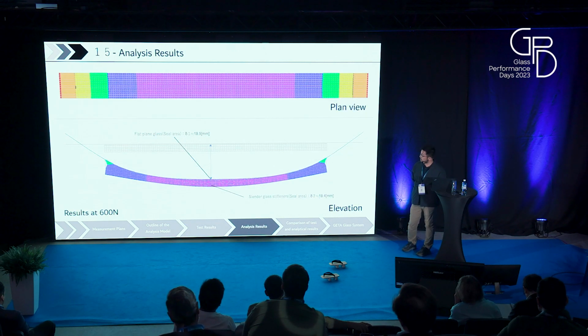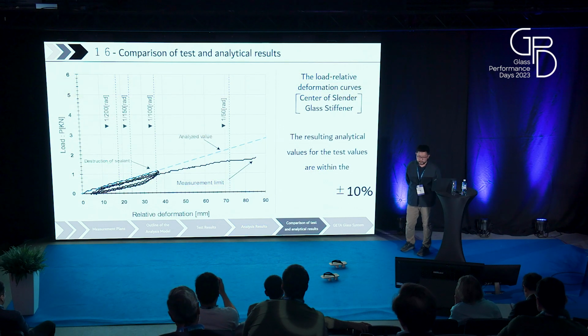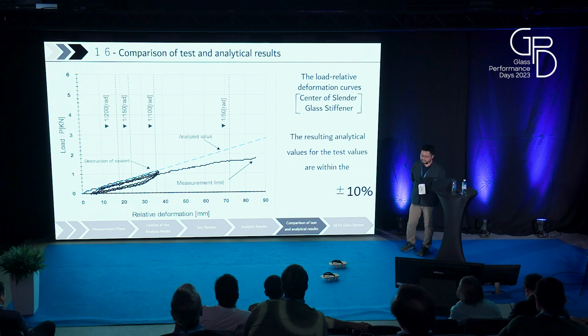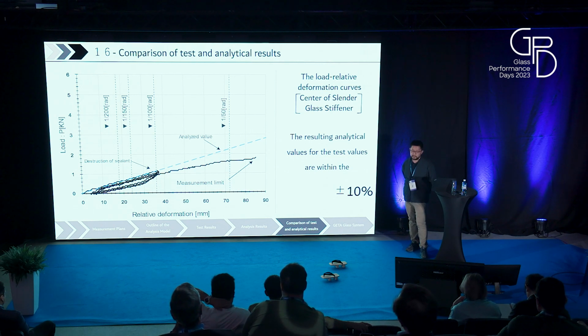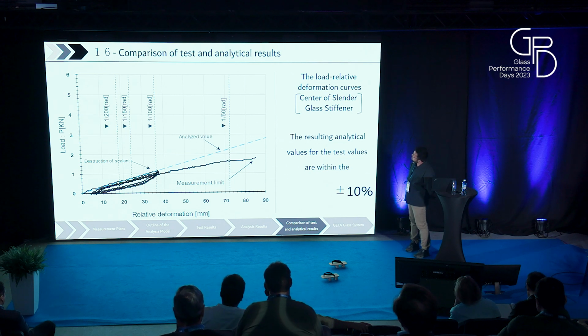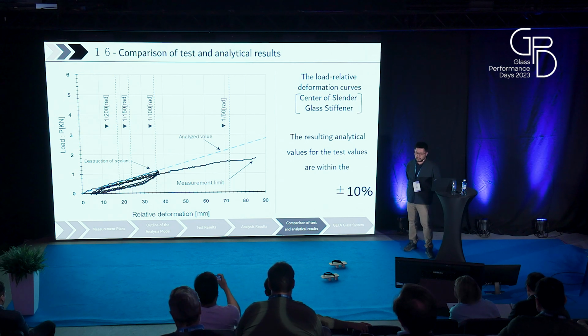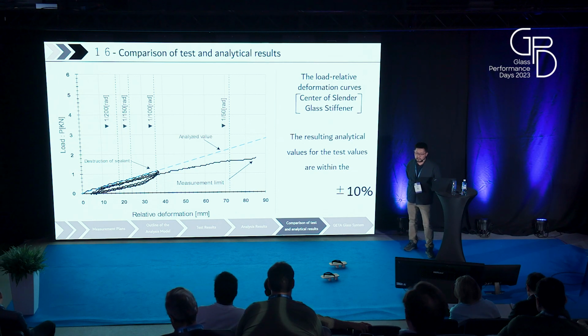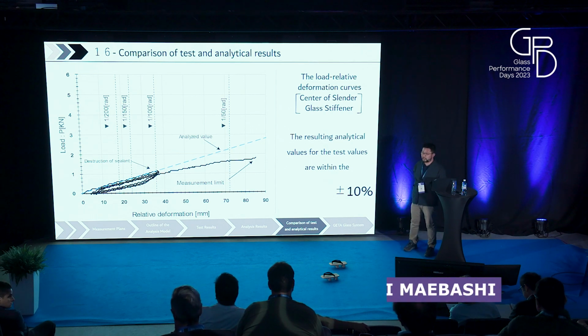And this is the analysis result. Also, we have compared the analytical values and test values obtained from the bending load experiments, and here are the analysis results. As a result, we could confirm that the difference between the test specimens with flat glass at the spot point location and the initial stiffness of the analytical model was within the range of 10%.